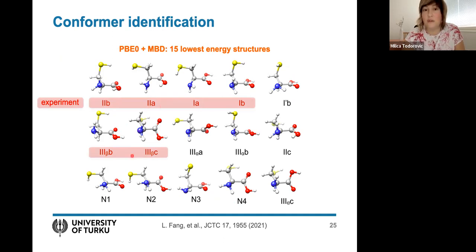So it's really good to know that in some active learning search with a few DFT calculations, you can recover all of the experimentally measured structures just from one active learning search. And then the other ones we found were also found in other computational studies before. And then we even found some new ones, but they were higher in energy, so we're not sure that they're really useful.